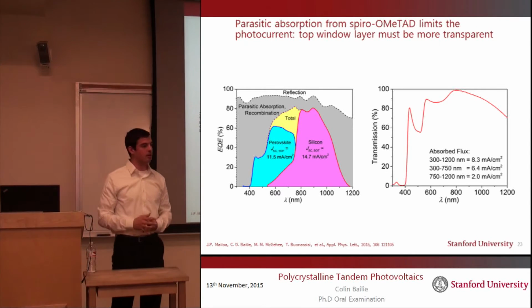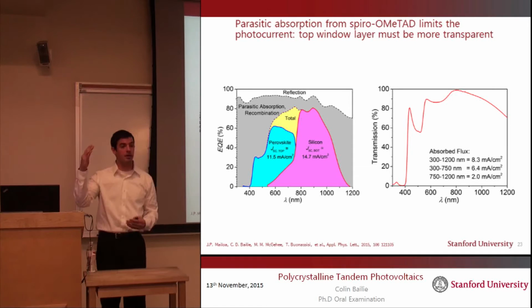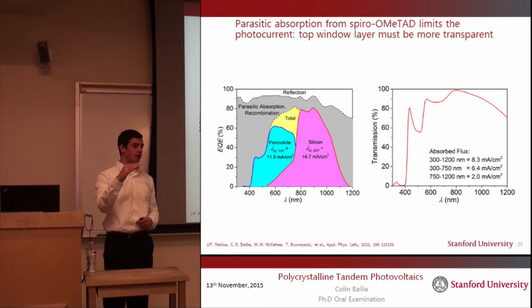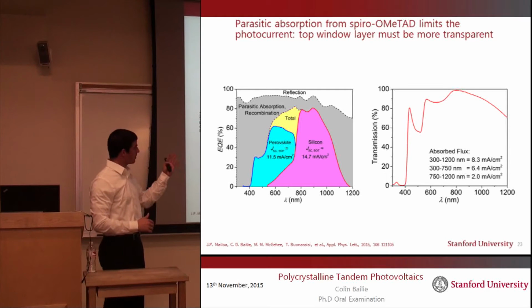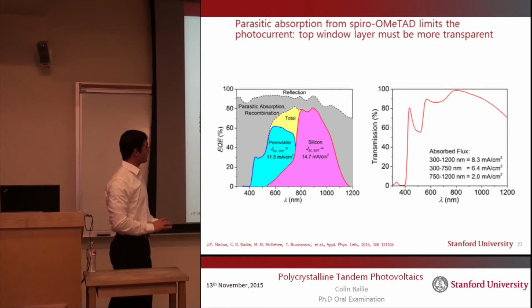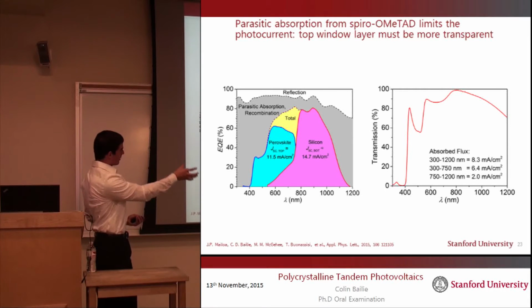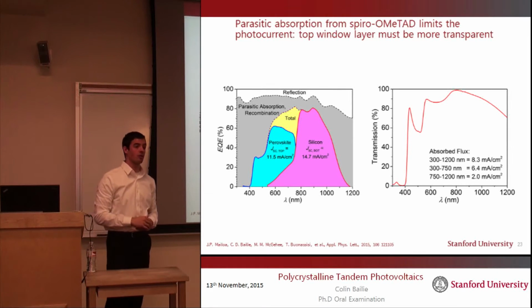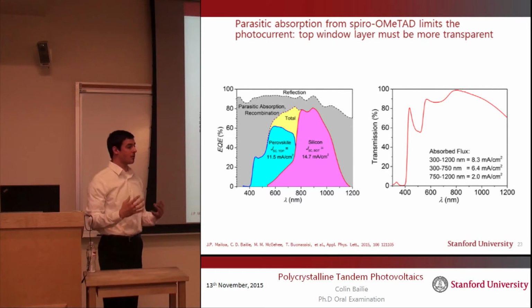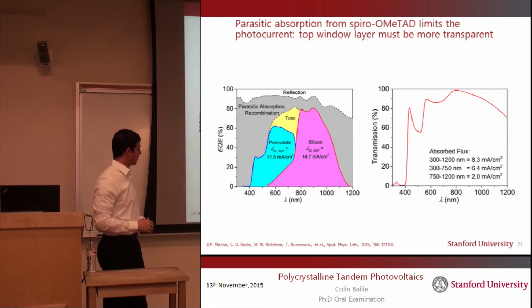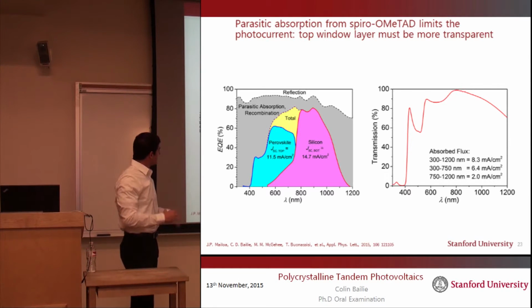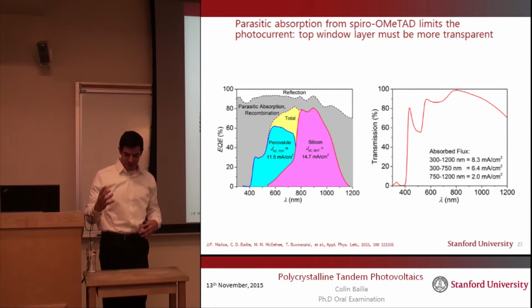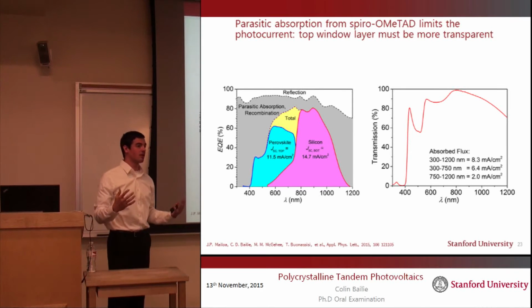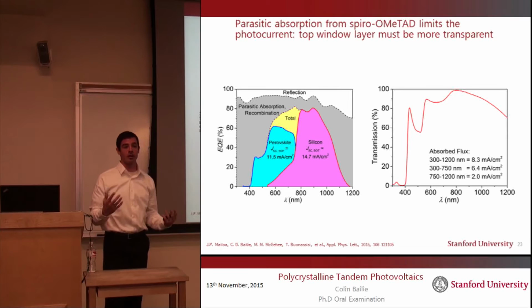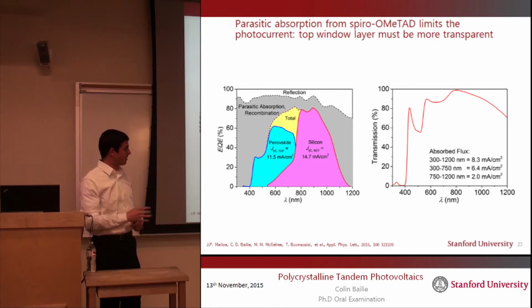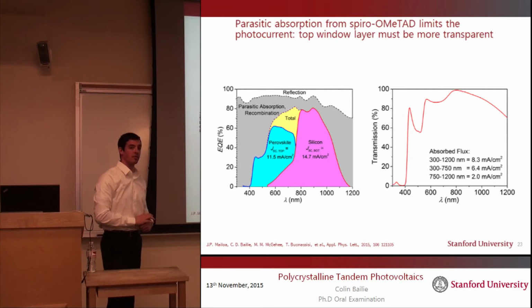But the reason that didn't happen is because when we built our NIP style perovskite solar cell, that P layer was spiro-OMeTAD. And the transmission of a doped layer with spiro-OMeTAD is on the right. And you can basically overlay that transmission curve with the gray region in the quantum efficiency plot on the left and see why the perovskite wasn't getting as much light as we might have wanted it to. So the spiro-OMeTAD layer was clearly not a good window layer, and we would like something that's more in the range of 3 electron volts and doesn't have any of this parasitic absorption throughout the visible and the infrared.